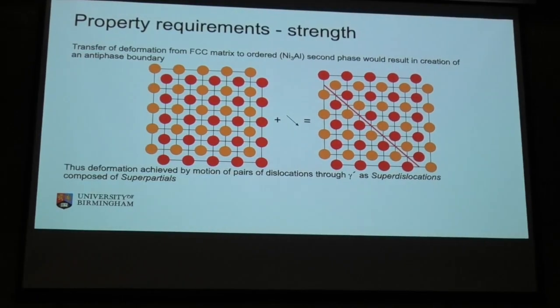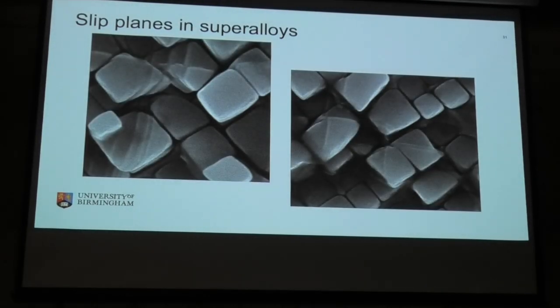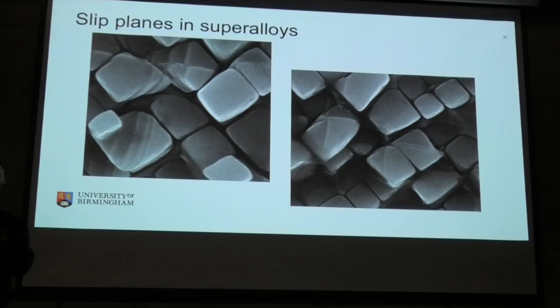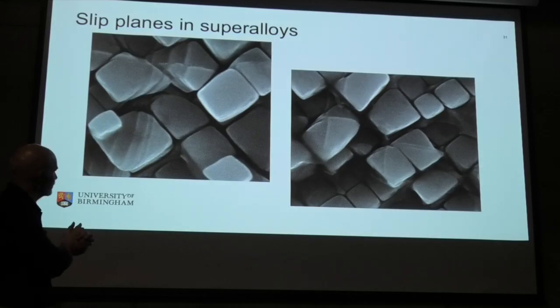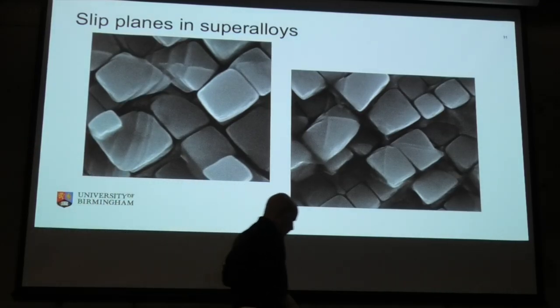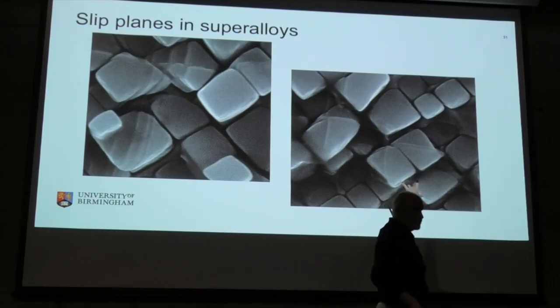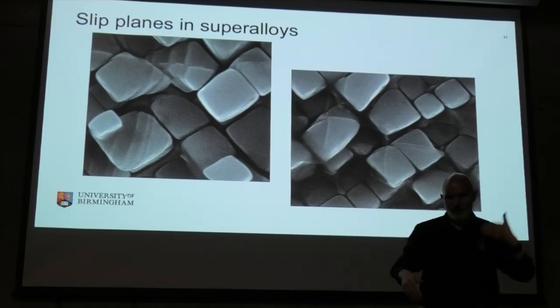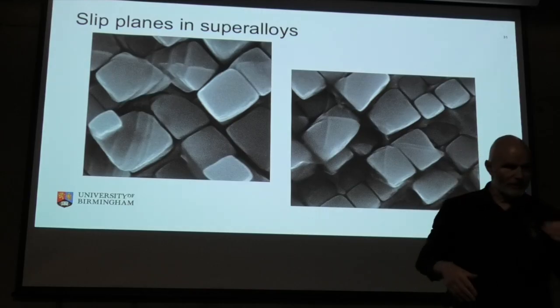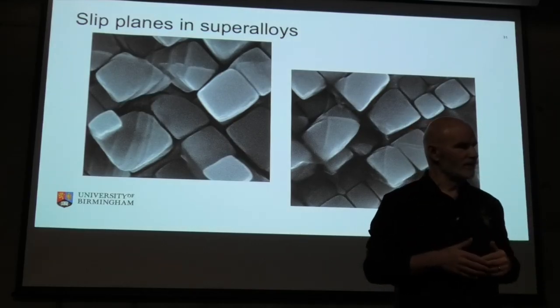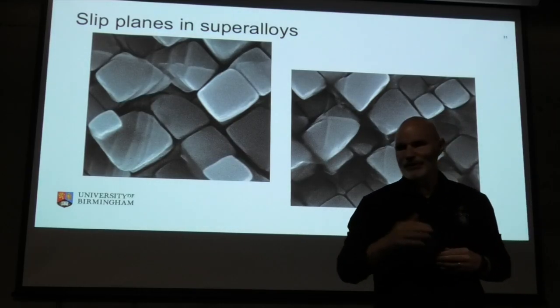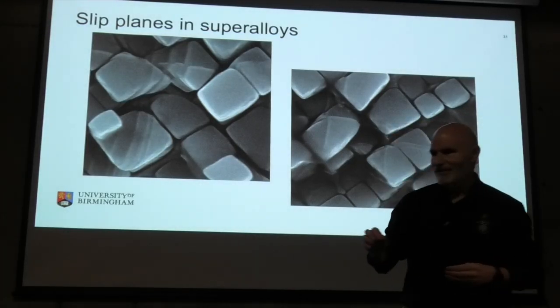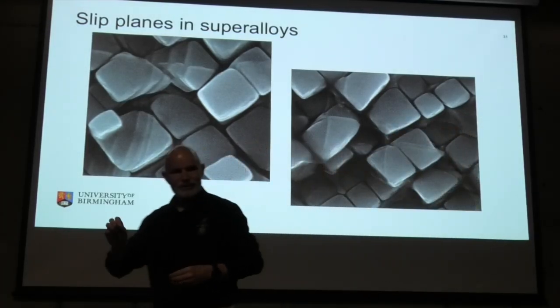And that's basically what happens - you have to send through two dislocations. They're called super dislocations because they travel around in pairs, and that's the cubic precipitate. If you squint long enough, you can just about make out two white lines across there - that's two dislocation planes we've got in that precipitate popping out, getting them in pairs. So we can see them, we do know it's right, and we have imaged them - we aren't just believing our own happy juice, it does actually exist.